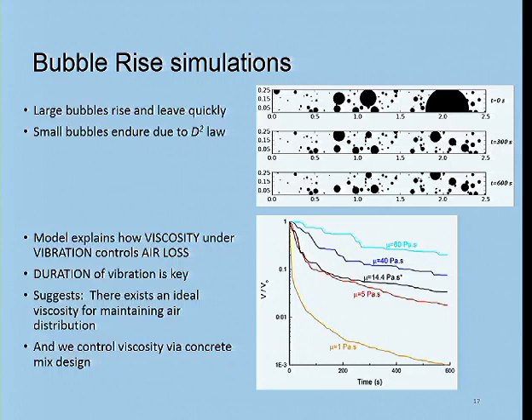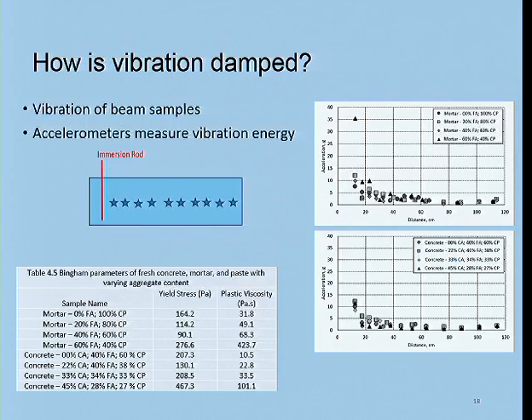And this chart tells us how viscosity plays a role here, that when we have very low viscosity, the timing has to be very, very short. If you have very low viscosity in your materials, you run into air loss here of a 99% air loss within a few seconds if your viscosity was very, very low. So anyway, we got our hands around this whole technical problem about the physics of that problem. And we did experiments on how vibration is damped by using accelerometers at different points along a beam that was vibrated at the end. And so we could see that kind of behavior as well, and that became part of our understanding of how vibration is propagated through concrete.